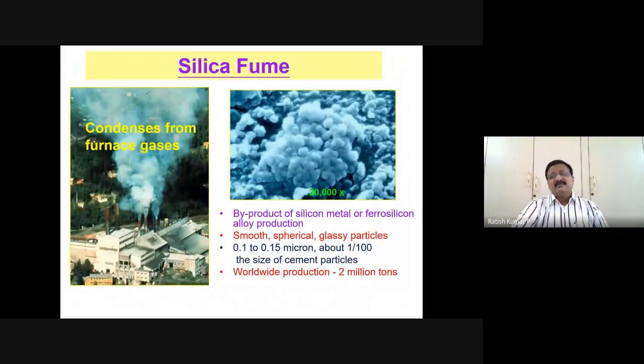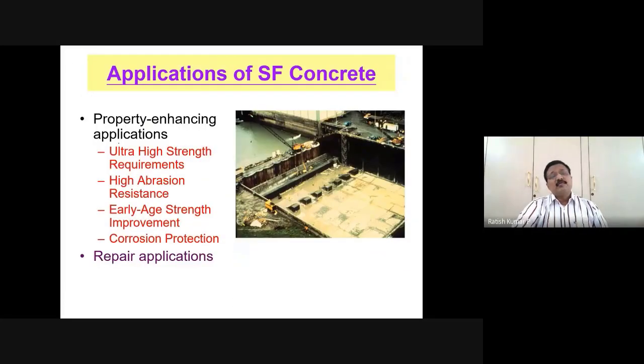Silica fume is one thing which is also available. It has very good properties, but the amount of silica fume is also very less. As I told you, it has very good properties from this point of view. It can give very, very high compressive strength, and with an 8% replacement or addition in cement, you can get strength of the order of 80 MPa, 100 MPa also. But again, this comes basically from ferrosilicon alloys. The amount available is very, very less.